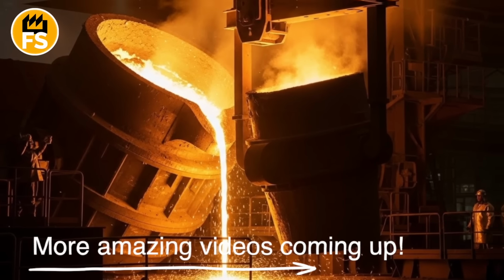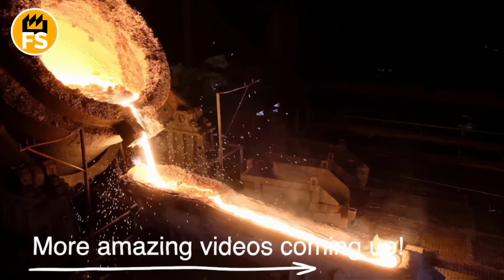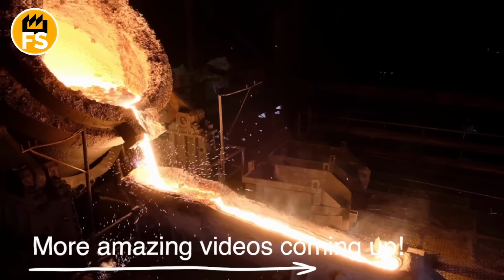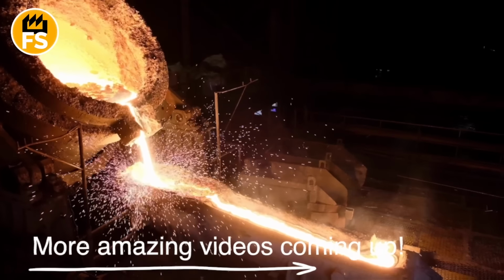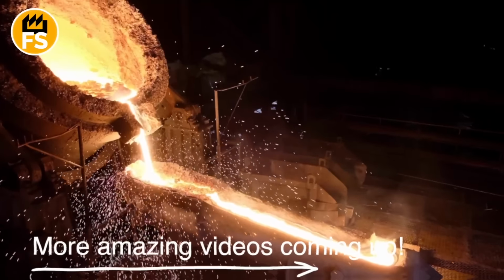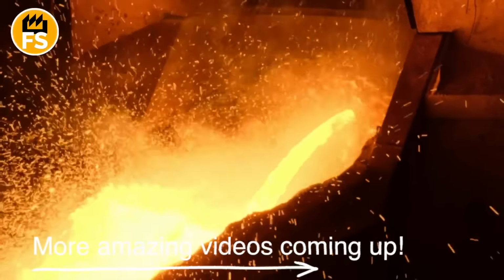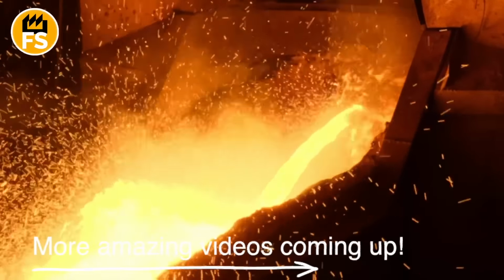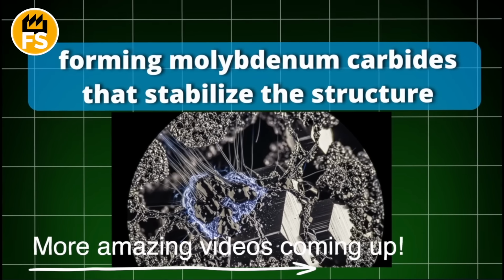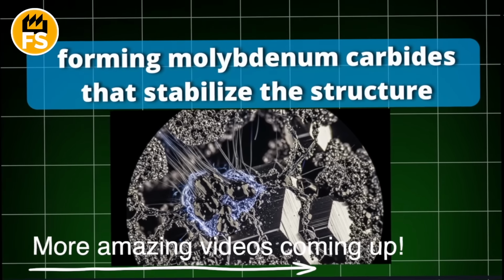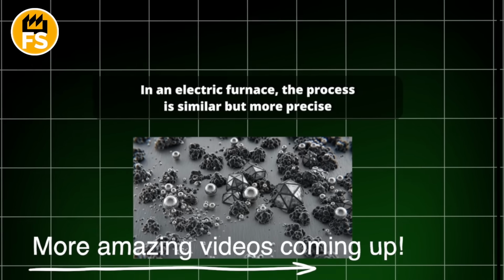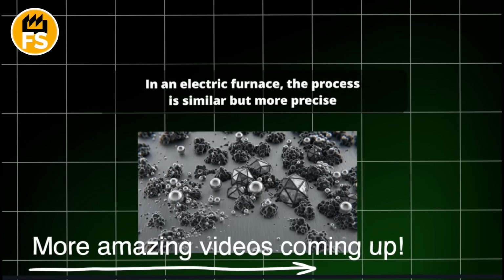The converter, a giant 200-ton vessel, gets filled first with molten pig iron from the blast furnace. Then cranes dump in scrap iron, coal powder for carburization, and batches of ferromolybdenum. The molybdenum dissolves instantly, forming molybdenum carbides that stabilize the structure. In an electric furnace, the process is similar but more precise.